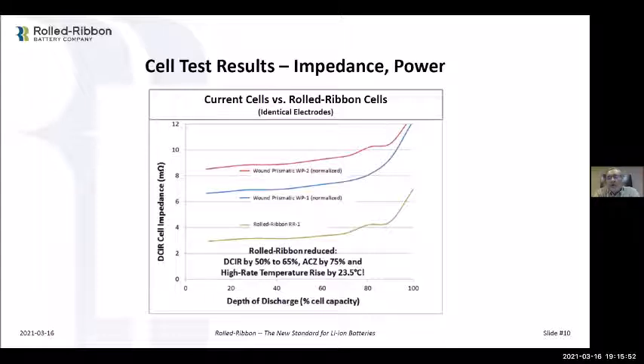Yeah. So all of those things I just explained, that's true for all lithium-ion electrodes. It doesn't matter what kind of package you put it in, whether it's cylindrical, pouch, prismatic, or rolled-ribbon. You make the electrodes in the same way. So you create a slurry, you put it on there, and the slurry has binder and solvents in it, and then you go through a drying process. In that process, you extract the solvents and bake it onto the foil, and then you calendar it to achieve your coat weight and press density without adversely affecting your morphology.